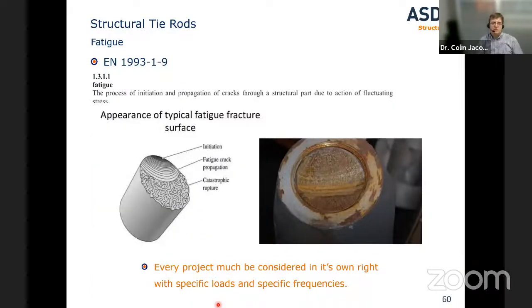So here's a typical failure via fatigue. So classic initiation, then the crack propagation, and obviously we get rupture towards the end. But every project really must be considered in its own right. It's very hard for a manufacturer to say, I have tie rods that are fatigue resistant, because it depends on your structure, what your loads are, what your cycles are, what your stress range is.